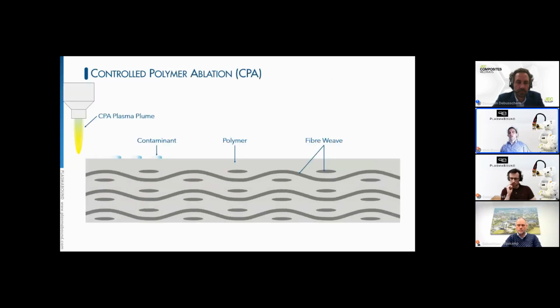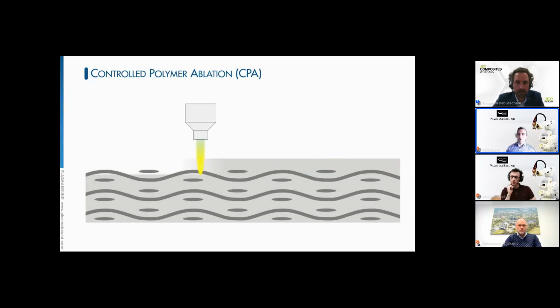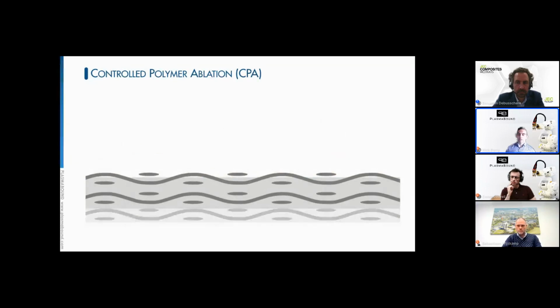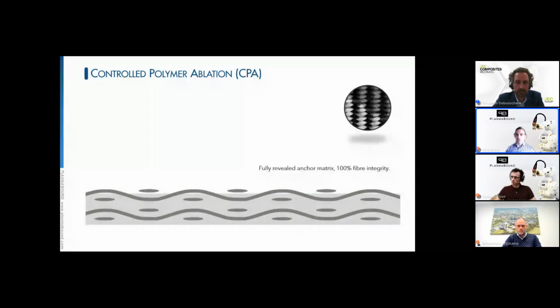If we take a newly fabricated FRP material with its contaminants, just as it's been pulled straight out of the mold, Plasmabound's CPA process can remove the top layer of the polymer and selectively expose some or all of the fiber structure beneath, while at the same time energizing the surface and simultaneously removing contaminants from the surface. On the top right there, you can see an epoxy system, where on the left of that image is the fibers free, and on the right, the fibers still remaining infused in the epoxy structure.